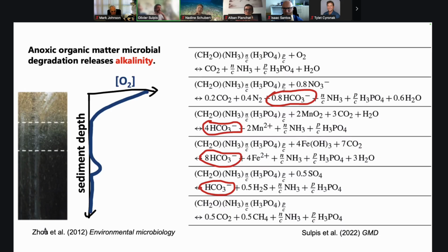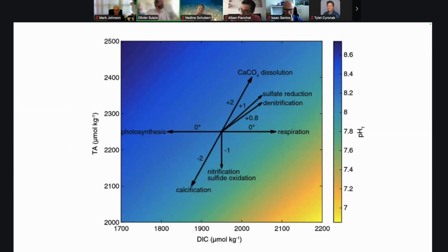And that's why it's important to keep in mind that in sediments, we have microbes there. When they work in the presence of oxygen, they mostly acidify the pore waters, and that would lead to the dissolution of calcium carbonates. But everything below, it's not that true. It could actually be the reverse. The fact that we have microbes respiring in the absence of oxygen could lead to preserving all of that calcium carbonate. So here we see again this plot that Tyler showed just before.